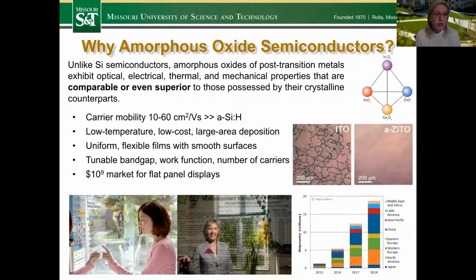So this is the first unusual quality of these materials, that, again, unlike silicon, we know that the properties deteriorate significantly when we go to the amorphous phase. Here, it doesn't happen. In fact, carrier mobility is on par with the crystalline phase, 10 to 60 centimeters squared per volt per second, and it's much, much greater than amorphous silicon even after hydrogenation.